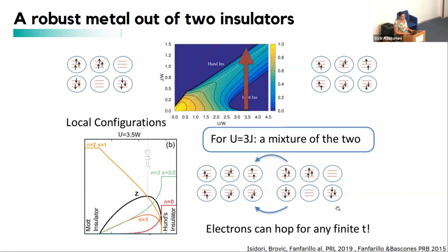So essentially, I think that what is interesting here is that strong correlation effects created 2 very strong insulating phases, but the competition between these 2 phases is creating a very robust metal. You can increase U at this point as much as you want, but the metallic state is extremely stable.